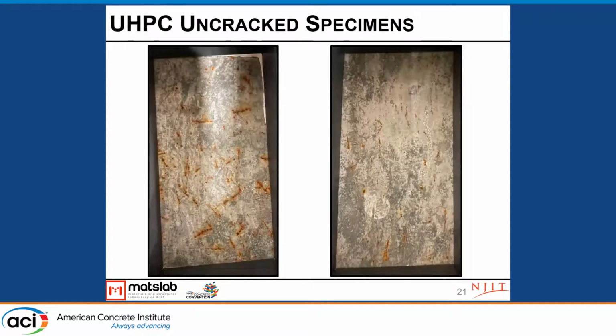At the very end, I have a picture, again the same view of the top of the dams, for two uncracked specimens. The reason I put this picture here is because of the rust you can see on the top of the specimens. If someone is unfamiliar with these materials and sees this surface on the top of concrete, they probably think we have some corrosion and these specimens are not in good condition, but it's not like that. It's just the very top surface of the steel fibers we have in the UHPC, and it has no effect on the corrosion performance or other things in the UHPC. I read in the literature that sometimes they can even have a positive effect on the corrosion performance of the UHPC because of the sacrificial anodes that we have with these steel fibers.